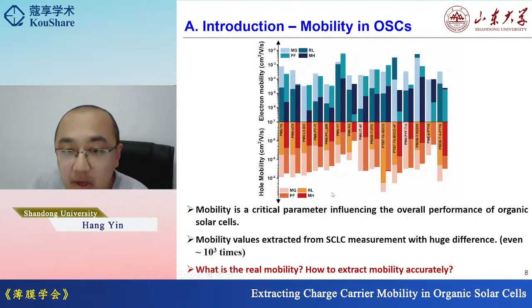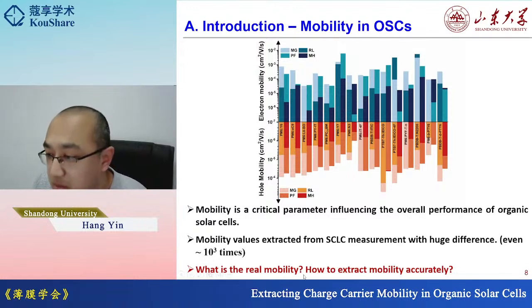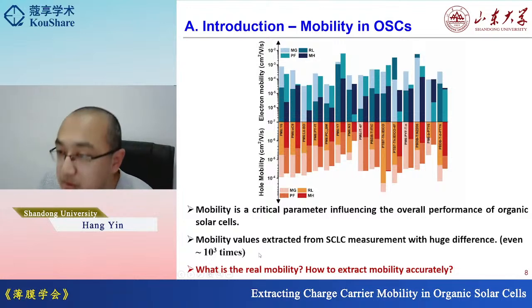We can see a very interesting example. We just summarize several typical bulk heterojunction systems and compulsorily fit the mobility values. We just fit, without confirming whether it's right or wrong. And we can see the results are quite different. So what is the real mobility and how to extract the mobility accurately? Because for the same JV curve, if you use different models, you can get a difference of even up to 1,000 times. It's very huge.